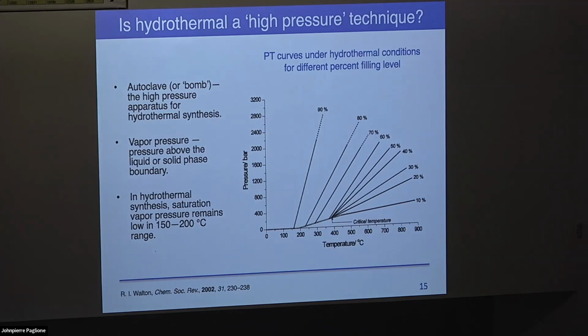So is hydrothermal a high pressure technique? It definitely is at some temperature regimes and with different things called filling fraction. I'll show you what that means. But for most of the syntheses that I did at the University of Maryland, and at Johns Hopkins, I mostly did all my syntheses below 200 C. So you can see the autogenous pressure is very, very low. So it's not necessarily a high pressure technique.